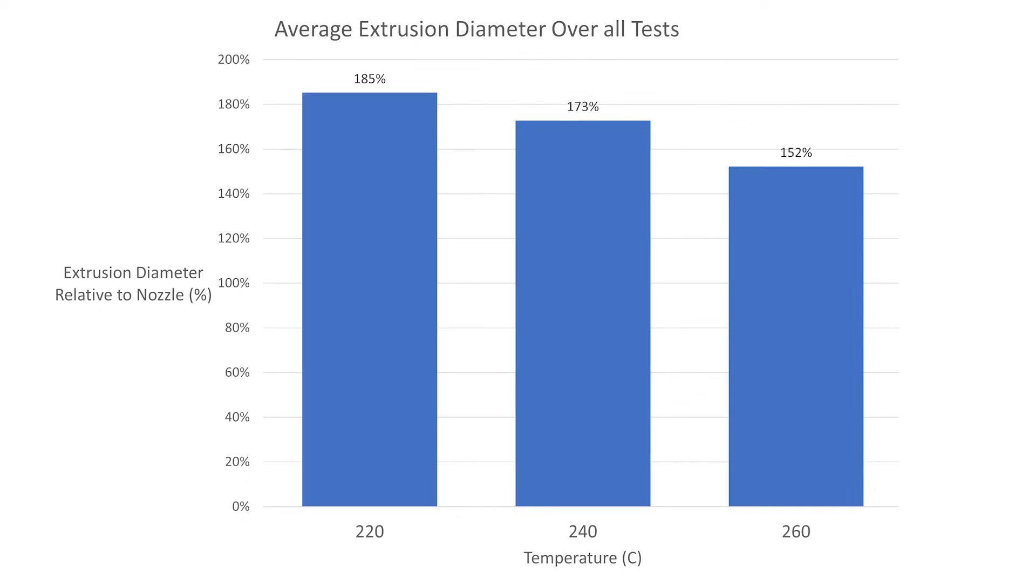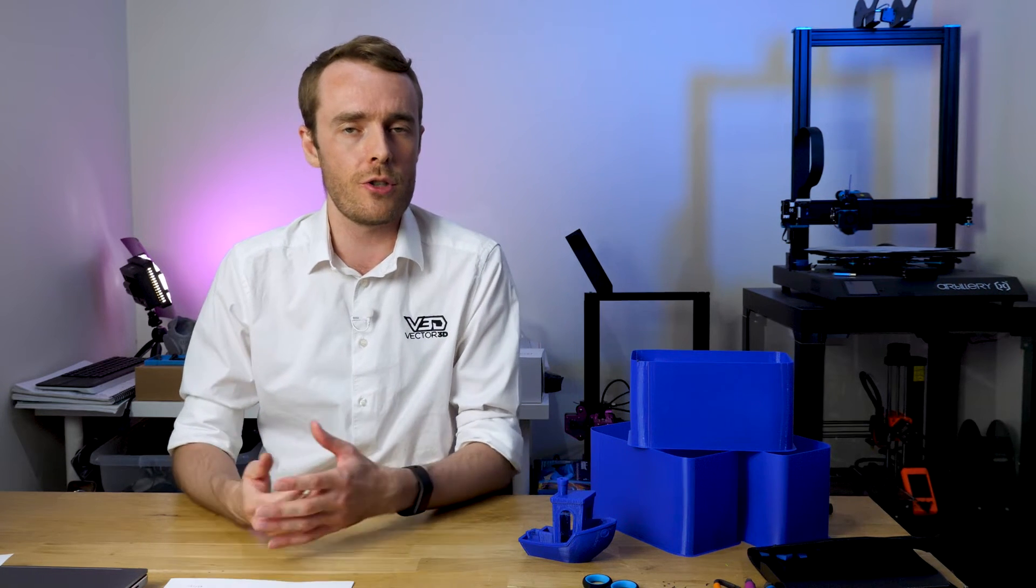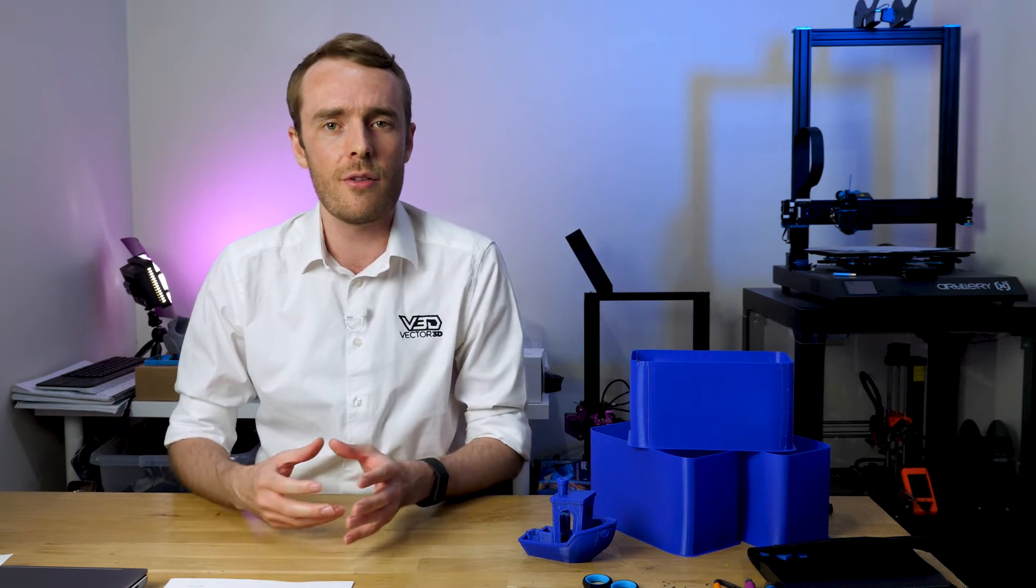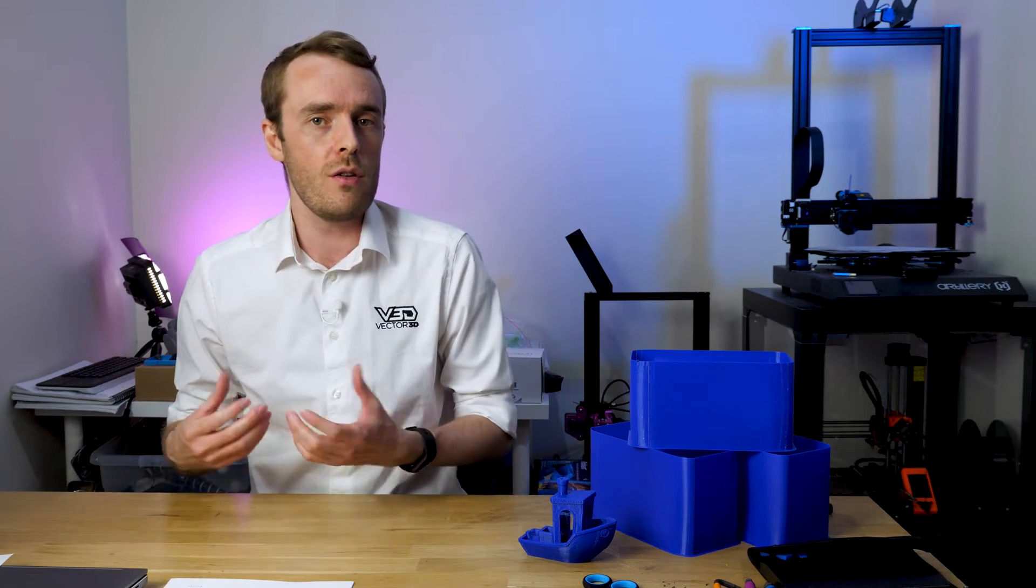If we take averages of the three series again, we can see that higher temperatures will indeed allow you to control the diameter of the extrusion better closer to the target. Although of course this is a free-forming extrusion diameter, so maybe not necessarily represented in the same way on a real print.